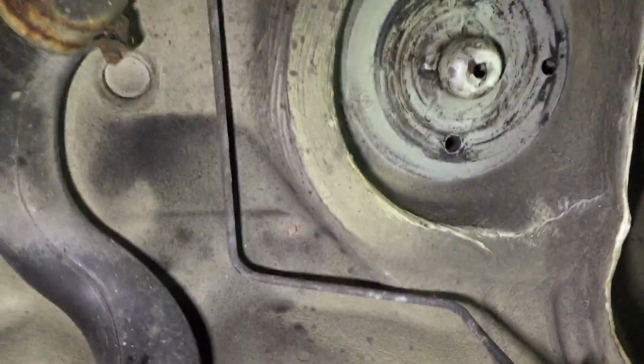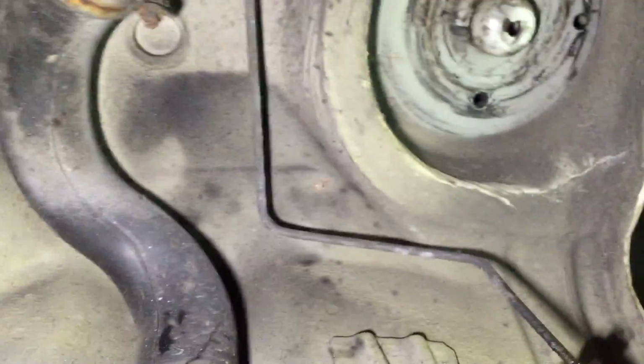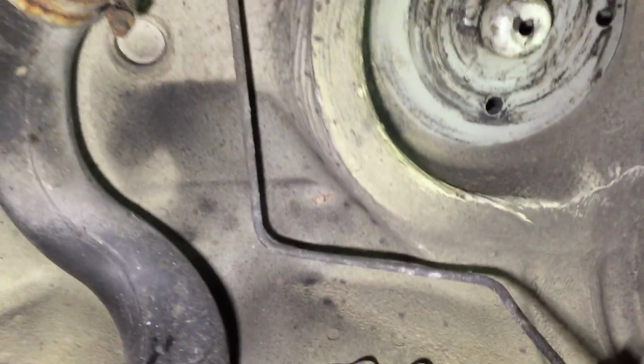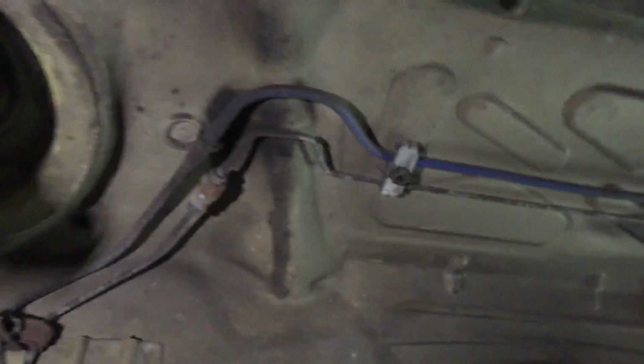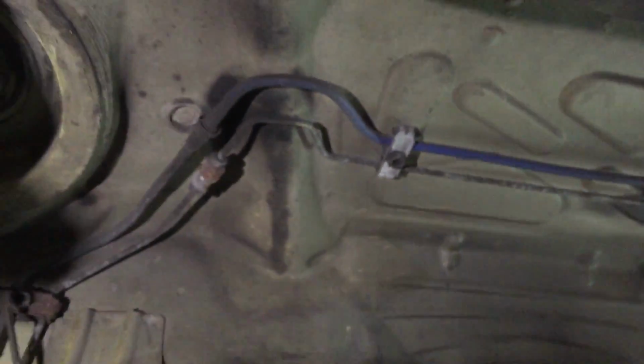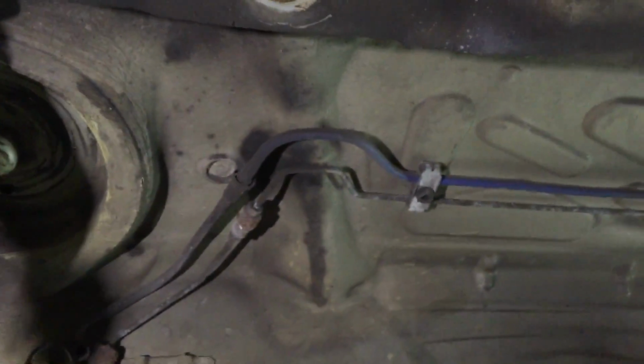Again, hard to see in this light before degreasing it, but there is a crack coming out of that spot weld, and definitely a spot weld break with quite a few cracks coming out of that one there, which is by the right front spring perch near the fuel filler neck and the brake pipe for the right rear circuit. So those ones are only achievable by drilling out and replacing the plug welds if we take some seam sealer